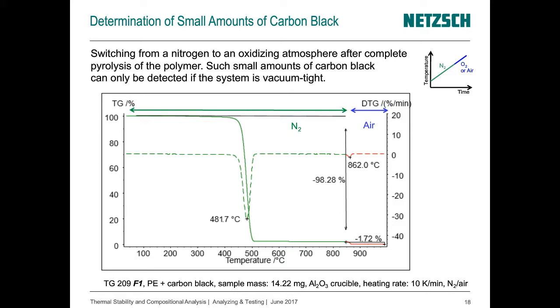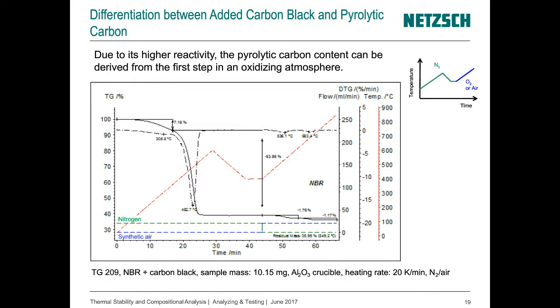But sometimes we don't have always base polymers which are decomposing completely in nitrogen atmosphere, but sometimes we also have base polymers which form so-called pyrolytic carbon. So that means that they don't decompose completely. And the question is now, is it possible to separate the amount of such pyrolytic carbon from added carbon black? And it is possible, but for doing this we have to modify the temperature program a little bit.